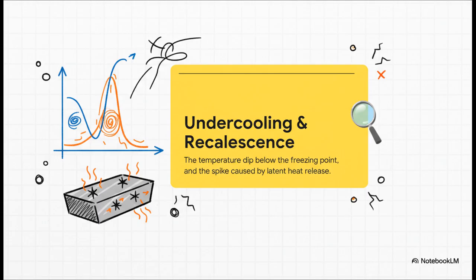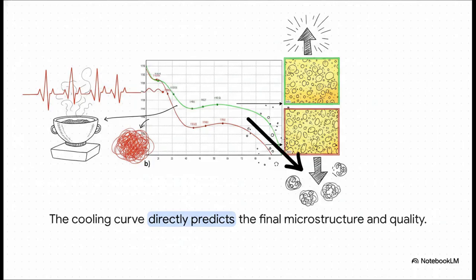Then you get recalescence, which is this awesome little temperature spike. That's from millions of crystals suddenly forming and releasing a burst of energy, which actually reheats the metal for a split second. The size of that dip and that spike tells us a ton about the health of the melt. And here is the proof.